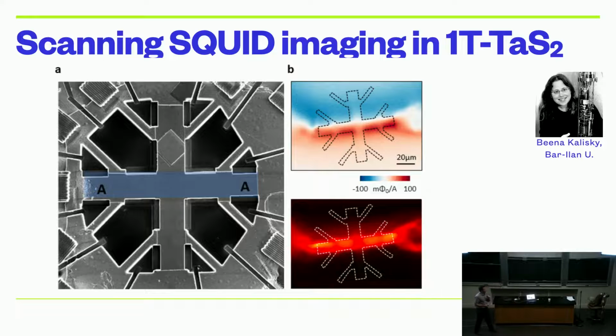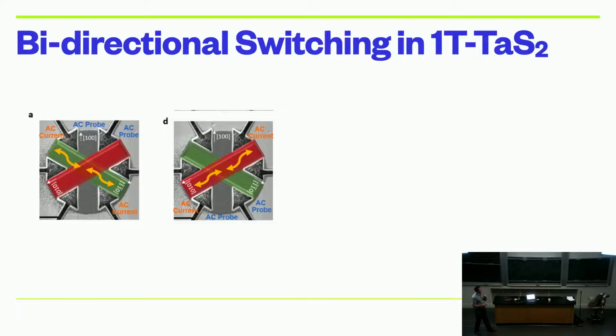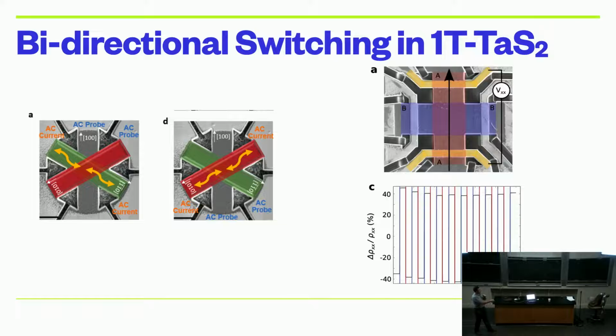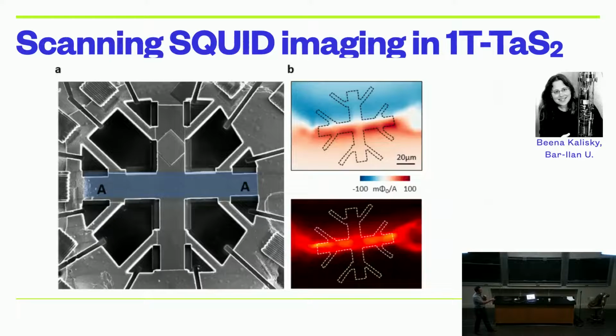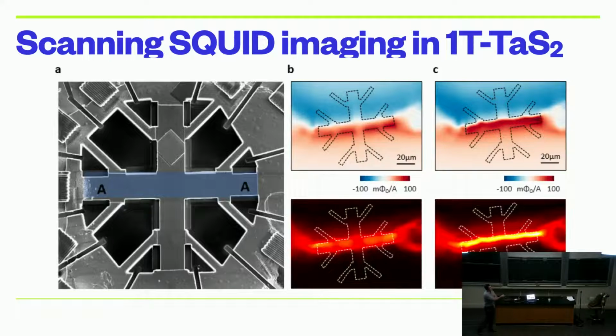What's happening when you pulse the device? Remember, we're going from low resistance to high resistance, low resistance to high resistance when we're pulsing up and down. Okay. So what she found is that once you pulse it and flood the system with a bunch of current, it localizes the current-carrying part to the edge, and the rest of it becomes an insulator and doesn't carry any current at all.